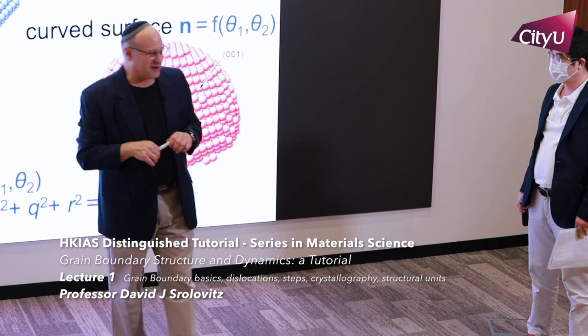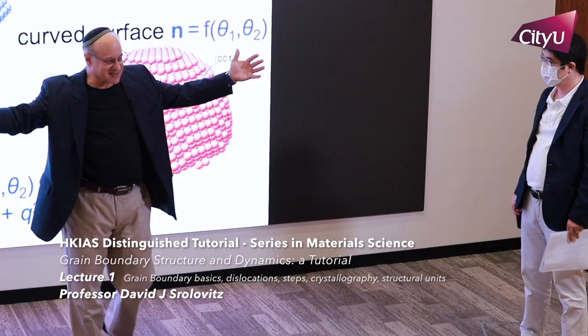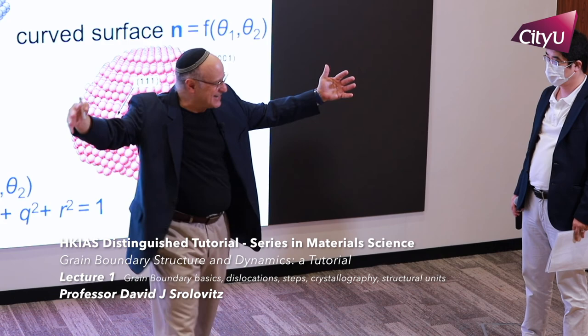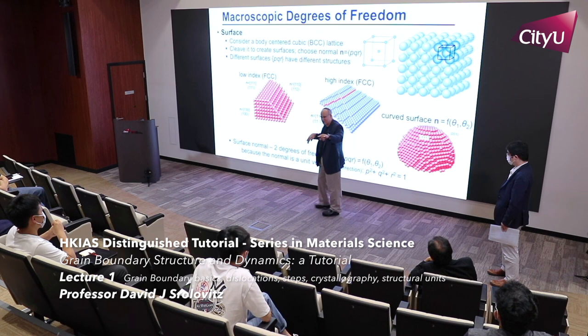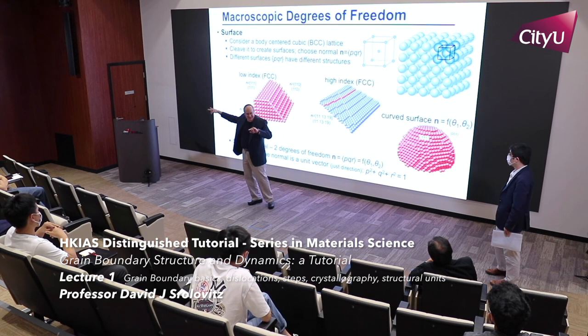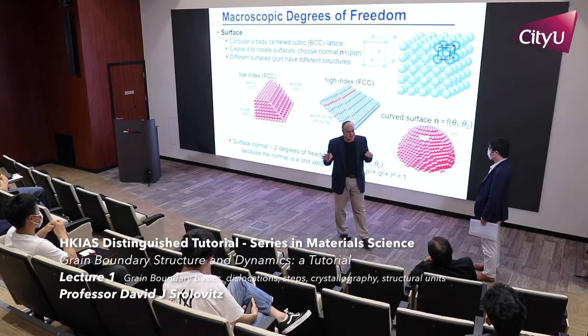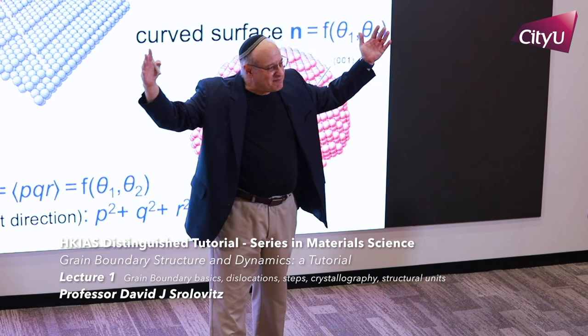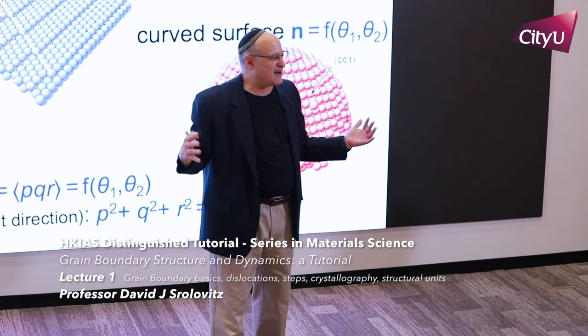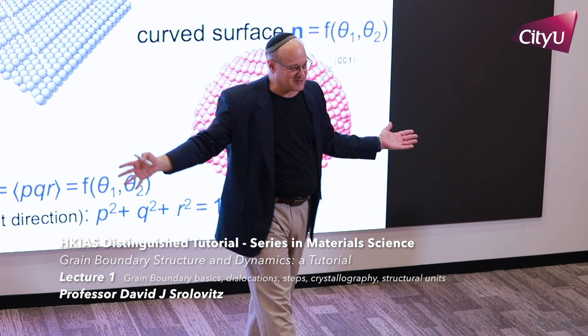But now if I go in and look at that boundary, which is 326,961, I know I said the same number twice, it looks exactly like the sigma 5 boundary along some distance. And then I have an aperiodic arrangement of something else in there. So I can think it's not periodic. So sigma itself is not a very useful thing. But if I want to understand the basic units of the structure, it's a very good way of doing it. I just have to realize that the whole structure may not really be periodic. So sigma itself is not a good variable.